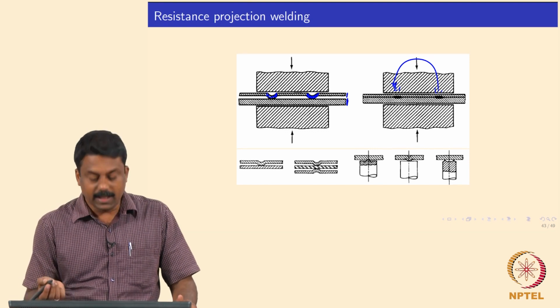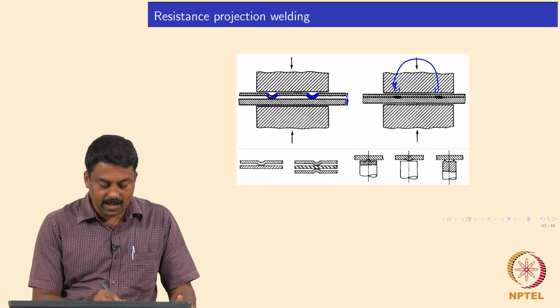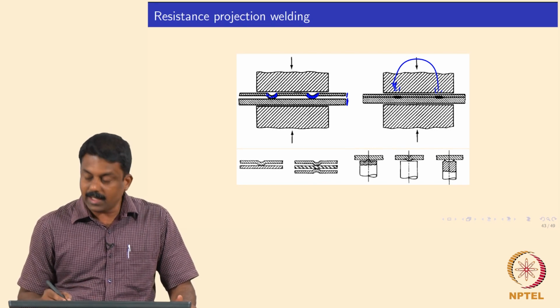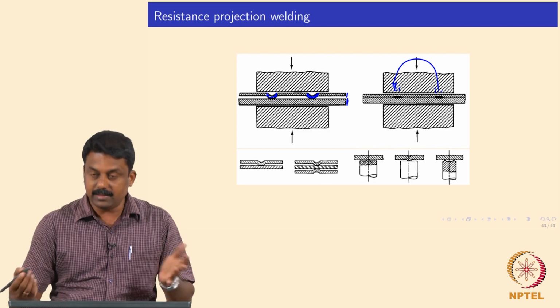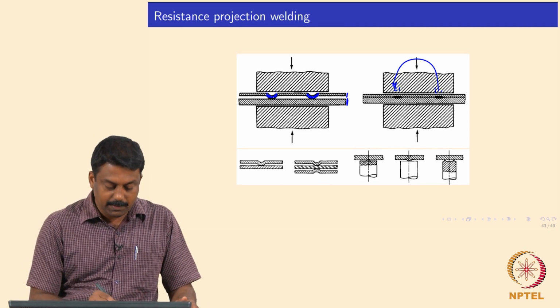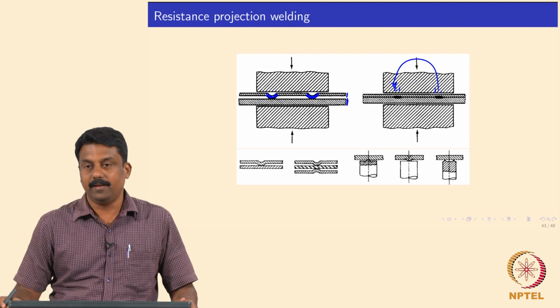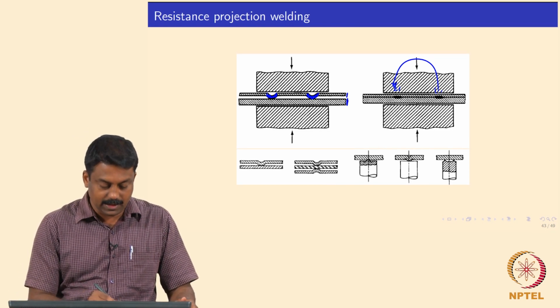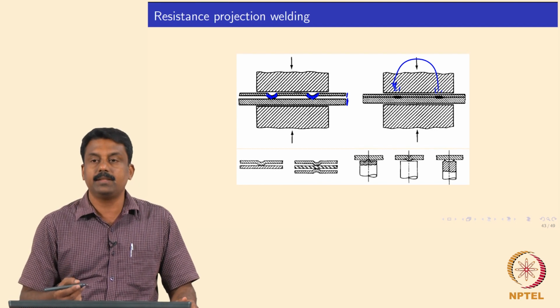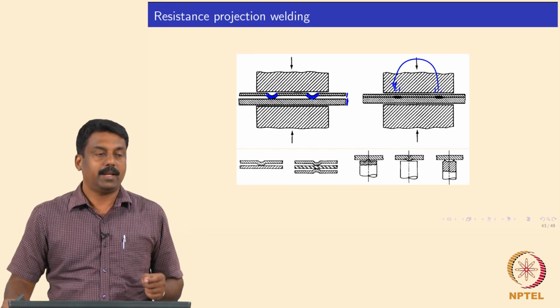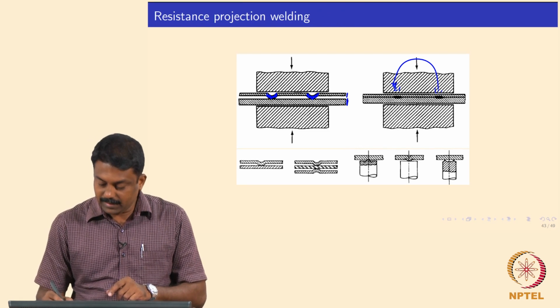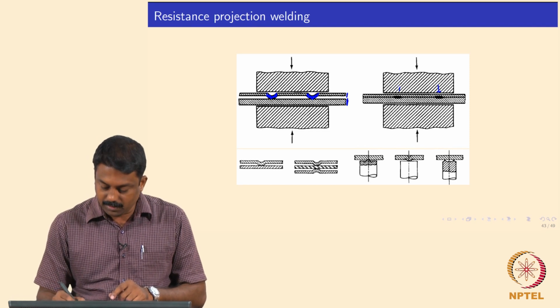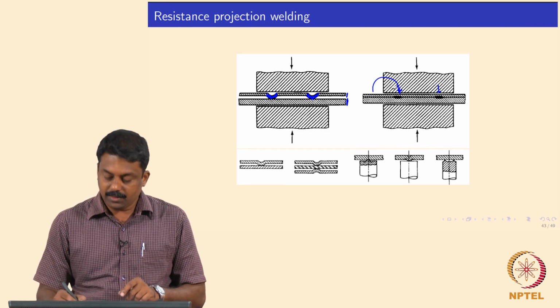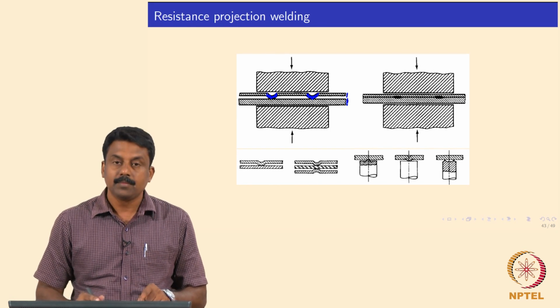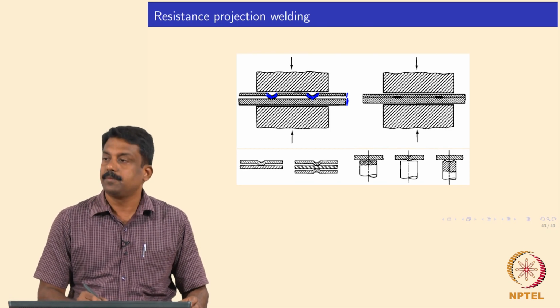So, instead of doing that, you can make some projections and have a larger electrode with a similar current density as in a resistance spot weld. You can do welding at multiple points, isn't it? The contact resistance and the contact area remain the same as the resistance spot weld. Instead of doing it sequentially, first a spot weld here, then moving over and doing it again here, you can use a slightly larger electrode by having a projection in one of the sheets.